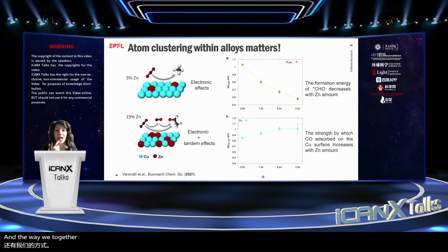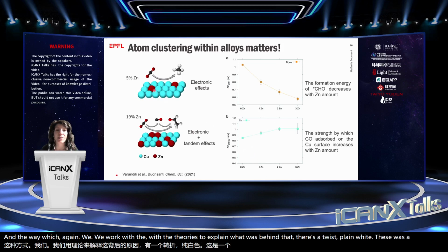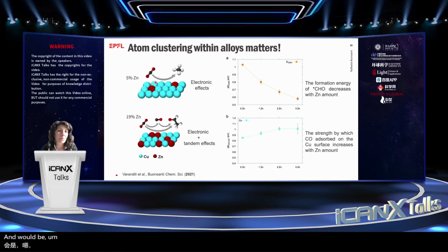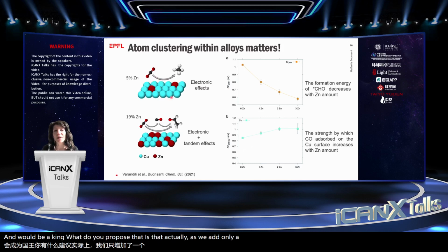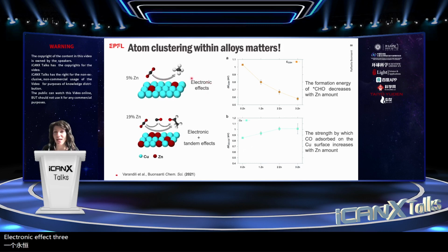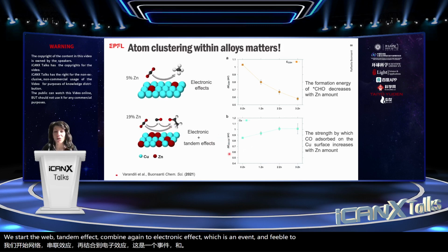And again, we worked with the theorists to explain why this was the case, and what they proposed is that as we have only a small percentage of zinc, electronic effects prevail, and these electronic effects stabilize the CHO intermediate, which actually favors methane formation. Instead, as we increase the zinc amount, we start forming clusters of neighboring zinc atoms. And as we form these clusters, we start to have a tandem effect combined again with electronic effects, which then eventually favor the C-C coupling.